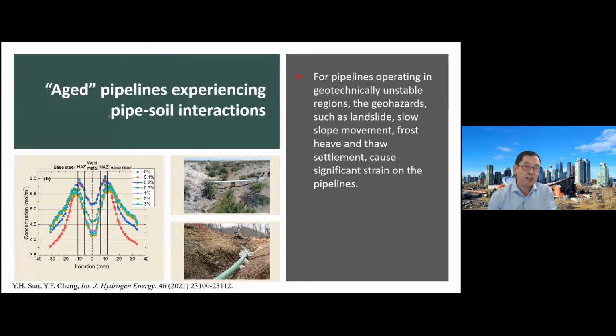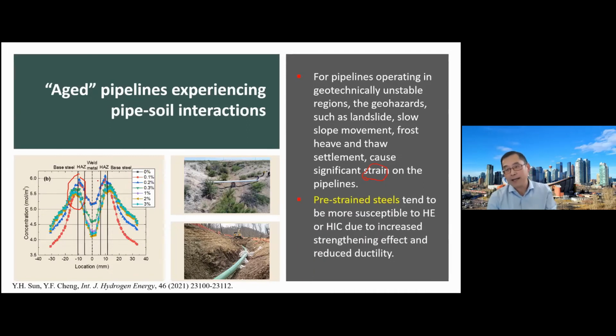The second extra challenge: after a pipeline is operated for many years, especially in geotechnically unstable areas, especially for Canadian pipelines operated in the mountain area and the Arctic area, the pipe-soil interaction can produce a significant strain on the pipe. From previous research, we do find a prestrained pipe steel will more easily attract more hydrogen into the steel. So the prestrain can increase the sensitivity of the aged pipeline to hydrogen embrittlement. That's the second additional challenge.